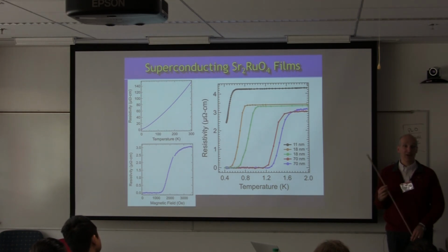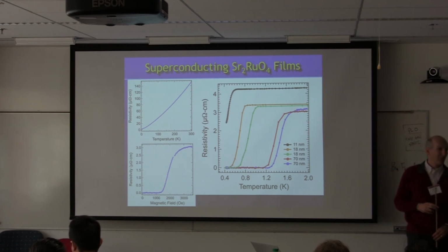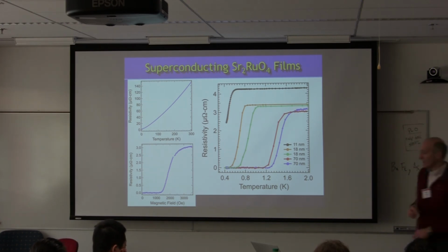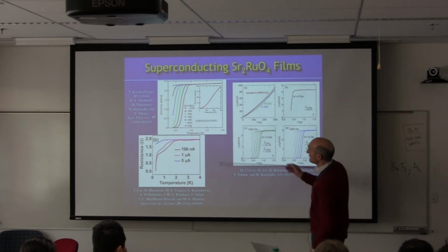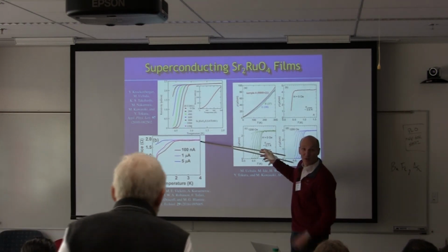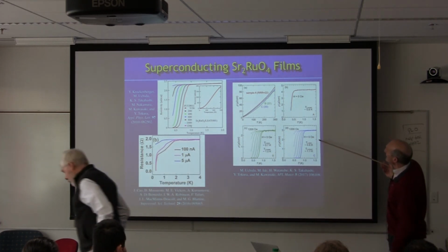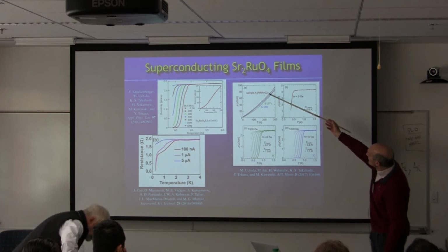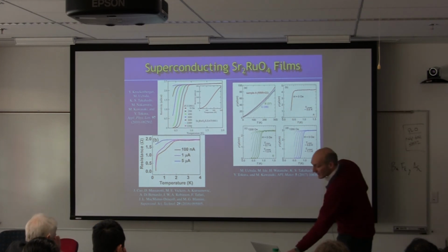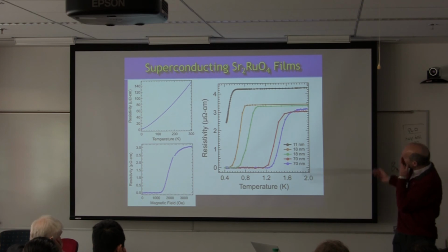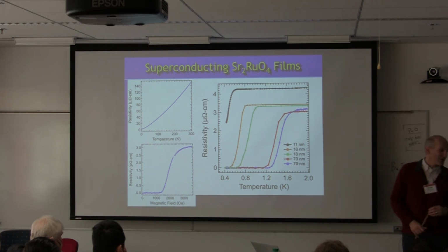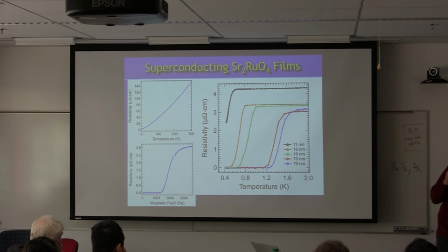The residual resistivity ratios needed in single crystals are about 80 before you start to see superconductivity. And the RRR, for example, of these films is about 4, where inhomogeneous superconductivity comes in. These have between 22 and 30. And our films have a max of now, we've gotten up to about 50 in RRR. So you are right that in single crystals, even higher RRRs are needed. I think the films can still be improved, but we do see superconductivity.